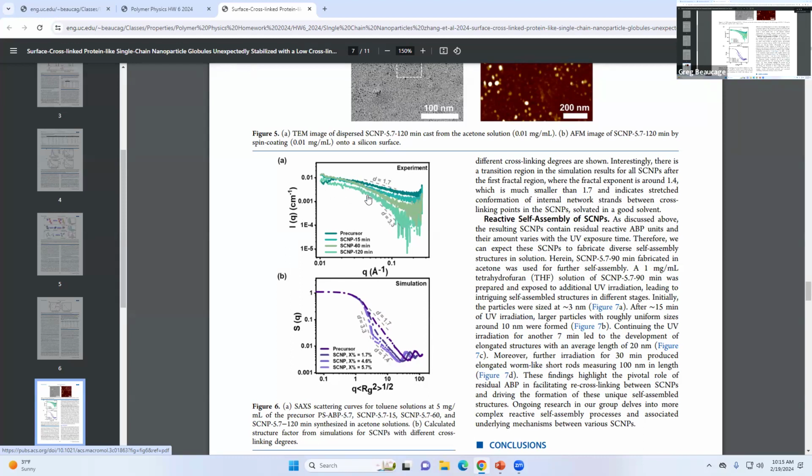Later on, maybe I'll show you how to get that law, but basically that's how to look at these. You look at a log-log plot, you're looking for the slope, so you get the power laws. You're looking for a 4 and you're looking for a 2. If you find the 2, this end of the 2 is the coil, and that end is the monomer, or whatever sub-particles make it up. When you find 4, that's a surface. The 4 ends at the particle size; 2 pi over that Q would be the particle size. So basically that's scattering in a nutshell.